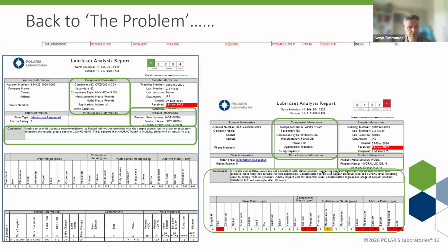So clearly someone's either topped up or used the wrong oil, and therefore our interpretation details that the viscosity and the additive levels aren't consistent with the stated product. We found ferrous wear, which could be coming from a variety of sources within the system, and the overall severity of the report is now red or critical or severe, which is a marked difference to the original report where we said it was green because everything was normal.